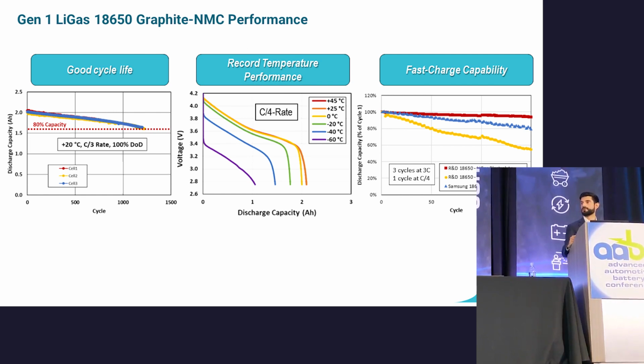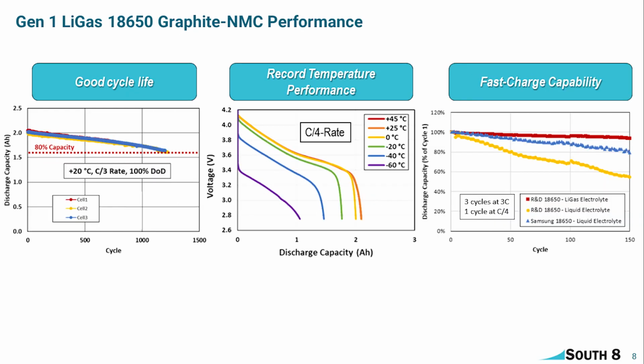Fast charge compatibility is great as well. Over here I'm showing three curves. The red curve is our LiGas electrolyte in an 18650. The yellow curve is showing an identical jelly roll with a conventional liquid electrolyte. We far outperform the liquid electrolyte on this fast charge schedule that we're testing here.